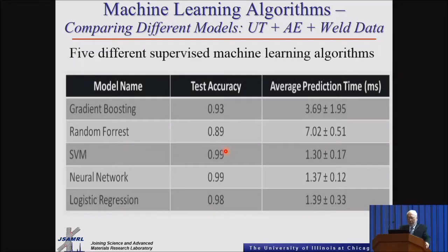We used models to assess the data, or to try to interpret the data that compares the UT, the acoustic emission, and the weld data. These were the 5 types of models: gradient boosting, random forest, SVM, neural network, and logistic regression. This tells you the accuracy, which is about 0.93, 0.89, 0.99, which was pretty reasonable. In terms of the average prediction time, in some cases we go all the way to 1.4 milliseconds, so it was pretty fast.